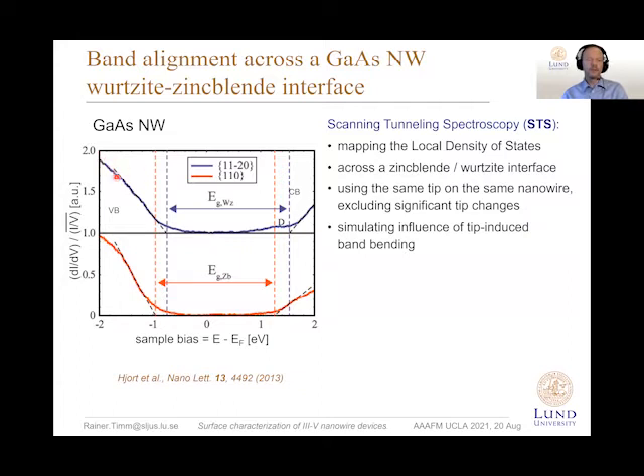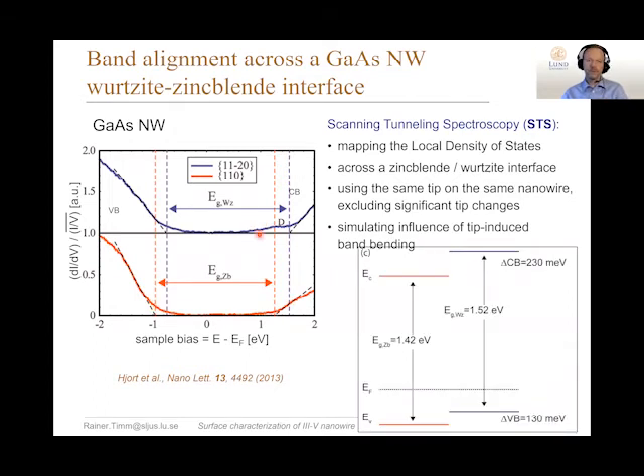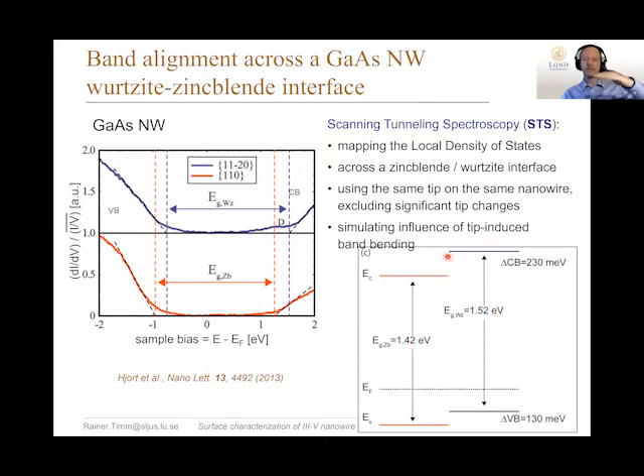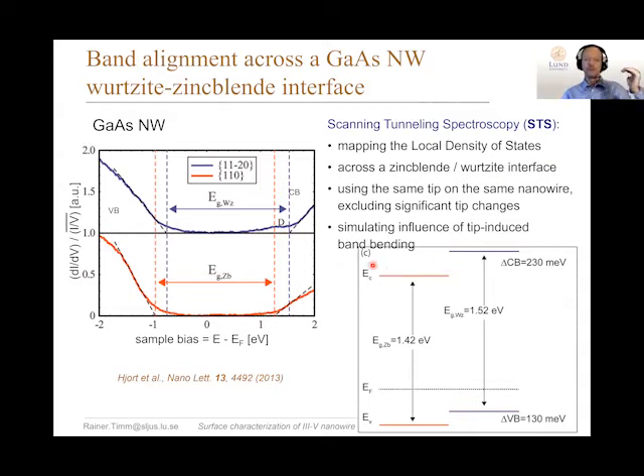This is done with these two spectra of the differential conductivity of our surface. You can see that the valence band offset shifts a bit between the wurtzite segment and the zinc blende segment, and the same for the conduction band offset. If we plot the band alignment from this data, we see that the wurtzite segment of this gallium arsenide nanowire has a slightly larger band gap than the zinc blende segment, and there is also a type-II band alignment — important for transport properties where electrons need to overcome this potential barrier.